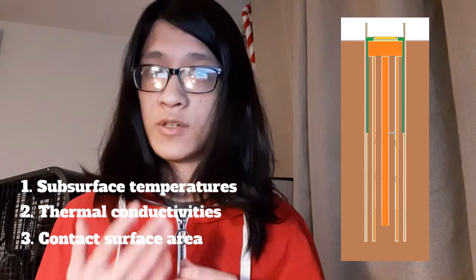Due to experimental limitations, we were forced to make several trade-offs during the design process. One leading trade-off concerned the length of our radiator cylinders and the resulting cost to manufacture it. Long radiator cylinders correlate with increased heat dissipation for the cold side of the TEG because of 3 interconnected factors that relate to increasing depth: the increasing subsurface temperatures, the increasing thermal conductivity, and the increasing contact surface area between the radiator cylinders and the surrounding lunar regolith.